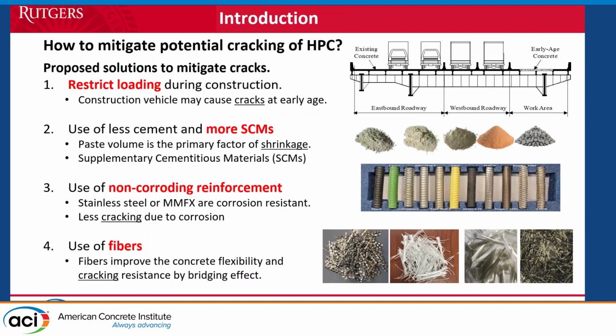So in that process, we also realized that no matter how good a concrete you have, if you have extremely heavy loads, that can be a problem, especially during the construction phase. Sometimes we realize that the contractor would use water tanks, a truck which is very heavy, to pour the water in different barrels for the burlap to keep it wet. Sometimes with the concrete itself, when it's delivered, it's very tight. They end up going into locations where it affects the load path, and the fresh concrete might be under stress beyond what it's designed for. So some of the cracking really happened at early age, and for reasons that have nothing to do with the mix itself. So the mix as a material was optimized for a lot of the factors.